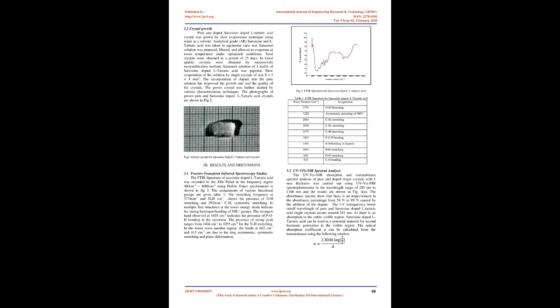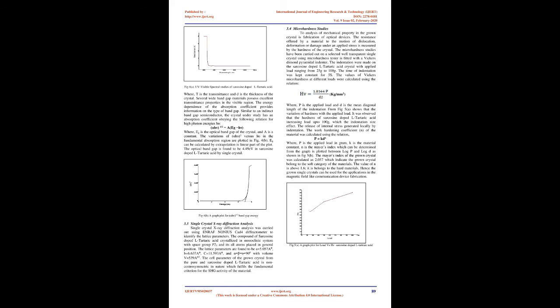3.2 UV-visible spectral analysis. The UV-visible absorption and transmittance spectral analysis of pure and doped single crystals with 1 mm thickness was carried out using a UV-visible spectrophotometer in the wavelength range of 200 nm to 1100 nm, and the results are shown in Fig 4a. The absorbance spectra show an improvement in the absorbance percentage from 58% to 89% caused by the addition of the dopant. The UV transparency lower cutoff wavelength of pure and sarcosine-doped L-tartaric acid single crystals occurs around 281 nm. As there is no absorption in the entire visible region, sarcosine-doped L-tartaric acid can be used as a potential material for second harmonic generation in the visible region.